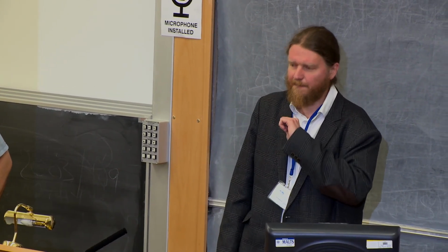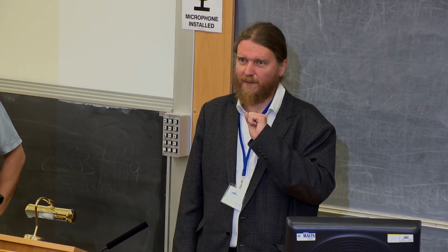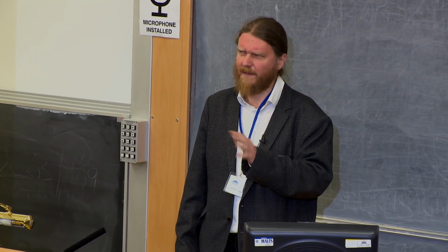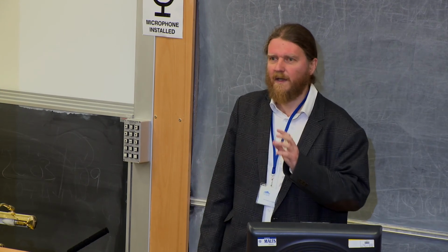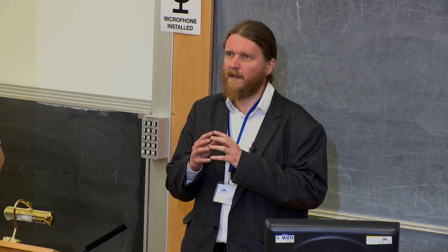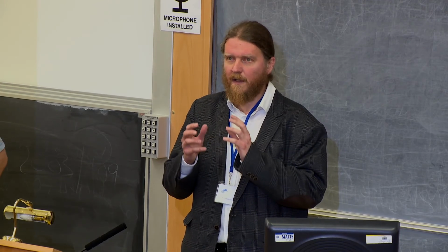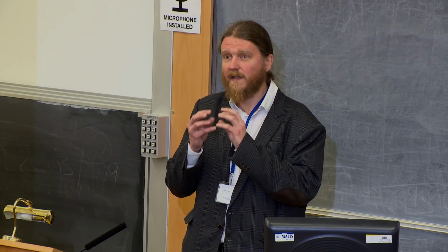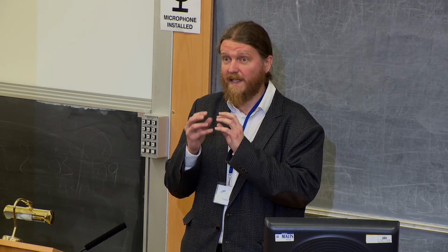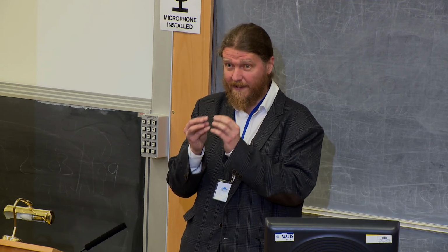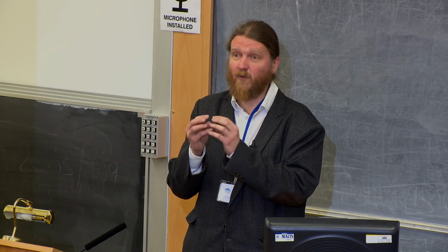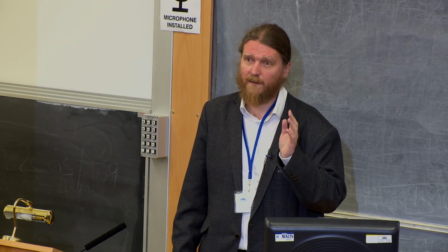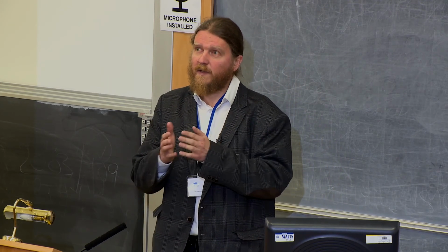In 1956, Julian Goldsmith from the University of Chicago published a paper about the simplicity of crystals, where he pointed out that if you have metastable crystallization, then polymorphs with smaller unit cells and lesser complexity would crystallize more easily, because the size of critical nuclei would be smaller. So if you are in some kind of metastable region of crystallization, so for example, this protodolomite,